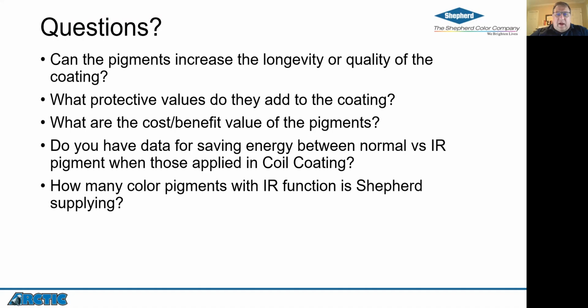How many color pigments with IR function is Shepherd supplying? We have a whole range of pigments that we call our Arctic pigments, from our blacks all the way through our yellows and all of our colors in between. The biggest gains are to be made in the black pigments, where you can go from a 5% reflectance for a standard black to a 25% reflectance for an IR reflective black. Yellows are inherently more reflective. Greens and blues are in between. So for our Arctic line, we picked the most reflective of each of the pigment classes and labeled those Arctic. But when it comes to formulating colors, you want to get the best black pigment in there, and we also have a number of other green pigments that are optimized for IR reflective properties.